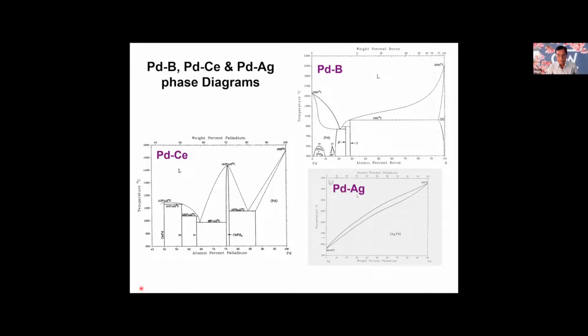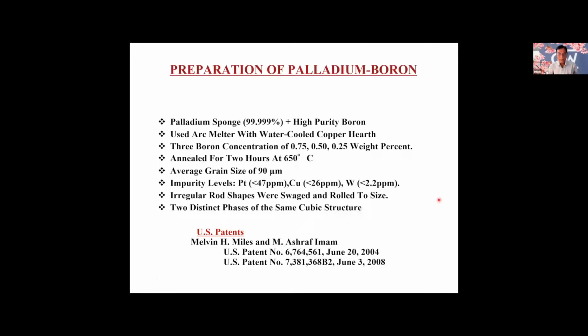So I just give you an idea how we made the palladium boron alloys. We took a sponge of high purity 5 nines palladium and then high purity boron. Then we used the arc melter with a water cooled copper hearth. Then we took 3 boron levels, attempting to have 0.75, 0.5, and 0.25 weight % of boron. After making it, we annealed it, and the average grain size is that one. The impurity level found is this much here, about platinum and copper and tungsten. And I will give you the details of the analysis also.